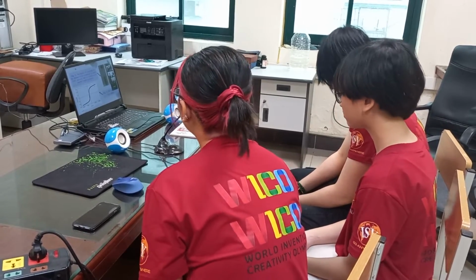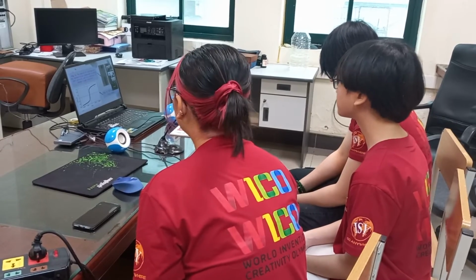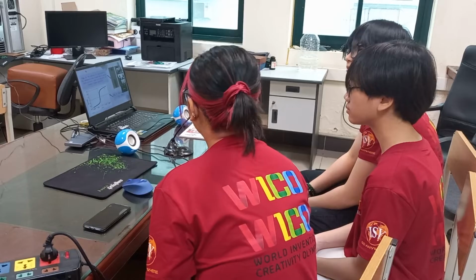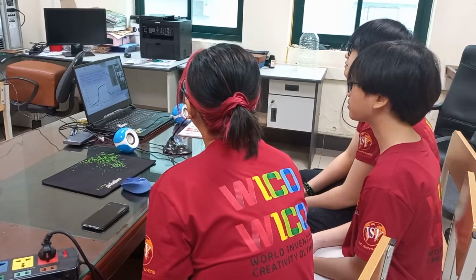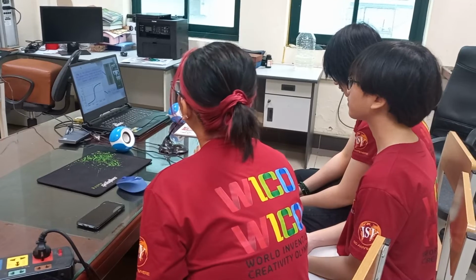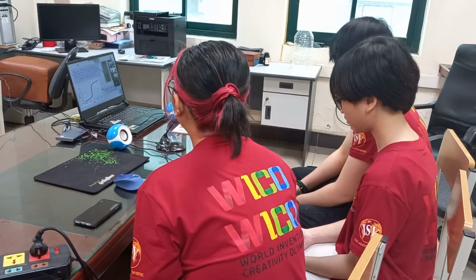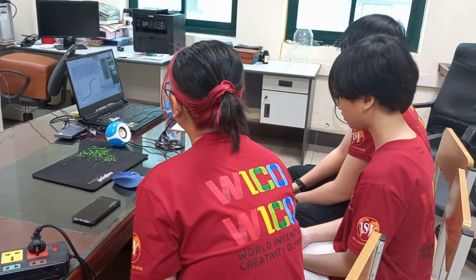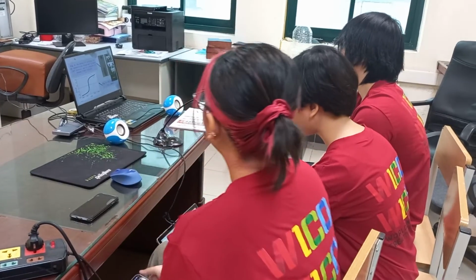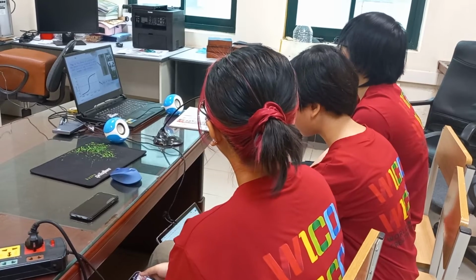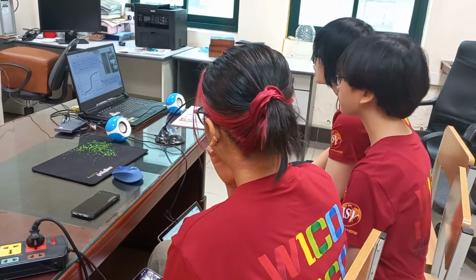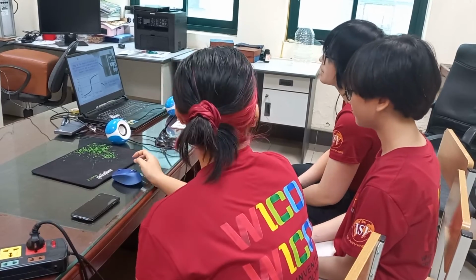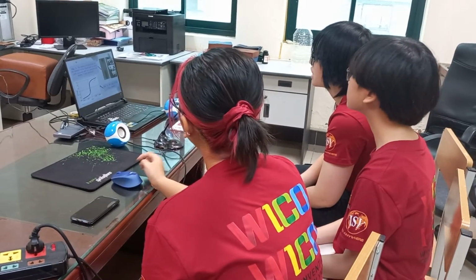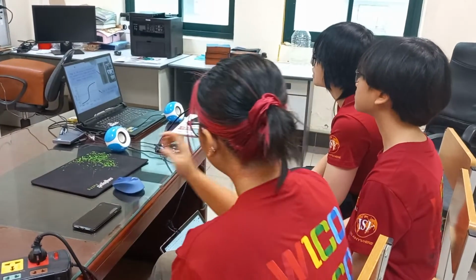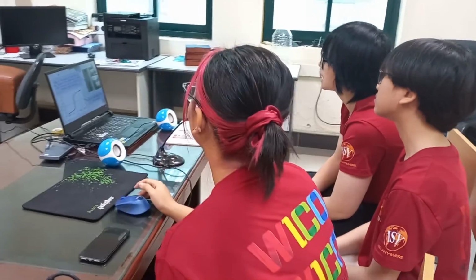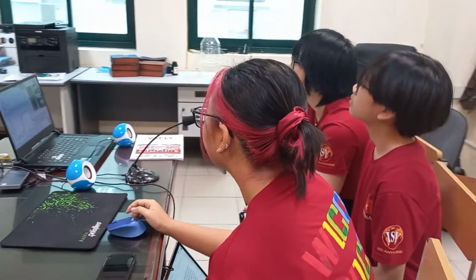As we have mentioned, the ferric oxide nanoparticles can be dispersed in water, and they can be transported easily throughout our bodies, hence be able to reach the injuries faster without being blocked by the digestive system. And the field-dependent magnetic measurement of the sample was carried out by a vibrating sample magnetometer. It appears that the ferric oxide is a superparamagnetic material, as the magnetization shows that it has approximately 60 EMU per gram.